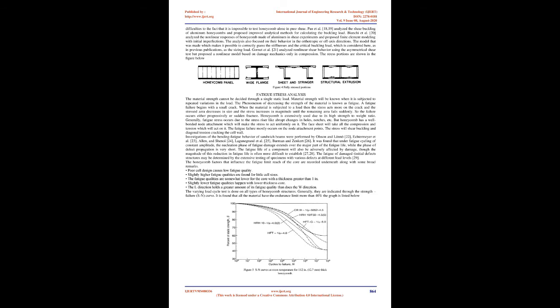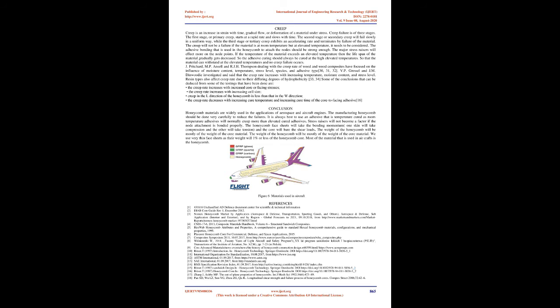Zhang and Ashby 17 then developed an analytical model based on the buckling formulas of plates, which allowed shear collapse stress to be calculated but did not investigate the nonlinear domain itself. They also stated the experimental difficulties, due to the fact that it is impossible to test honeycomb alone in pure shear. Pan et al. 18,19 analyzed the shear buckling of aluminum honeycombs and proposed improved analytical methods for calculating the buckling load. Bianchi et al. 20 analyzed the nonlinear responses of aluminum honeycomb in shear experiments and proposed finite element modeling with initial imperfections.